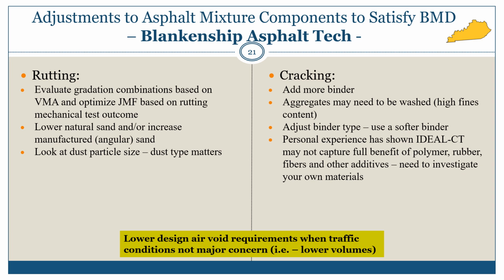He would ensure that you lower the natural sand content, increase the angularity as we saw earlier, and also look at the dust particle size. What he's seeing in Kentucky is that the dust type does matter in how the mixtures are performing from a rutting perspective. For cracking, he said the obvious one would be to add more asphalt binder, but he also said that some aggregates that have a high fines content may need to be washed.